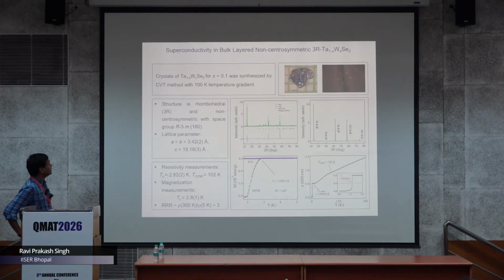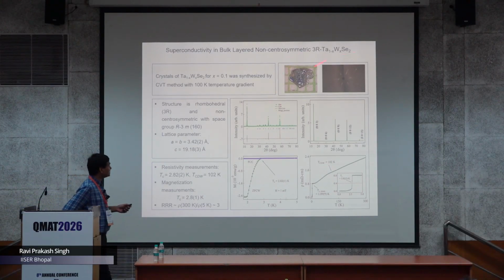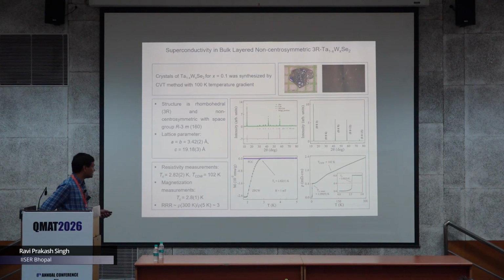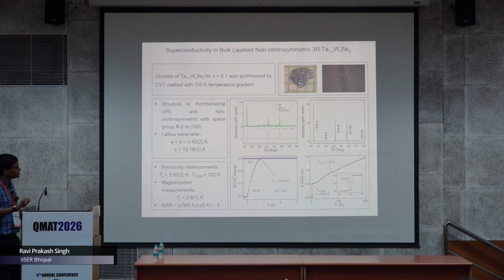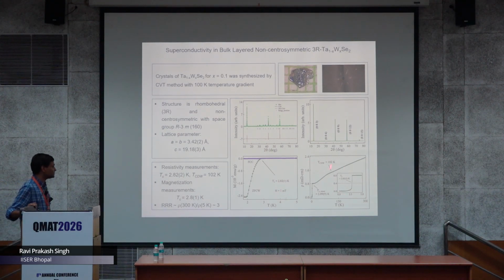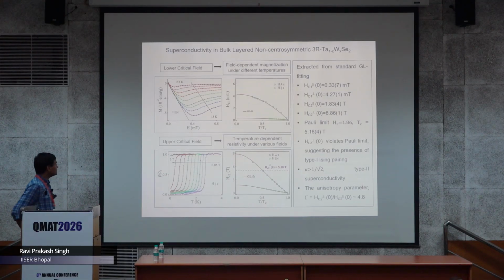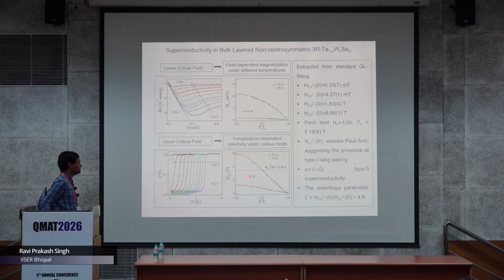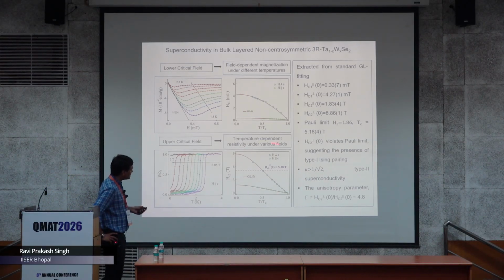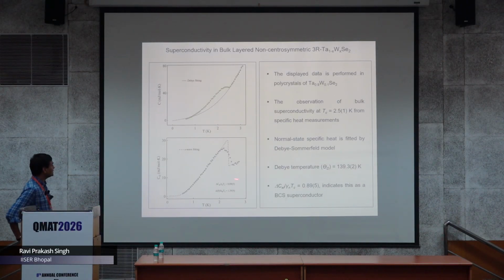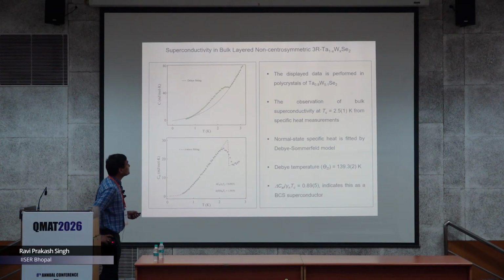And we get very nice crystals of this one, and Tc is around 2.8 Kelvin, and the charge density wave is present around 102 Kelvin. And here we found that Hc2 is nearly double, and it looks like Ising-type pairing is present. Heat capacity also shows S-wave behavior.